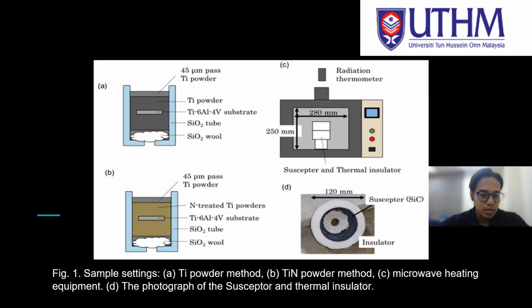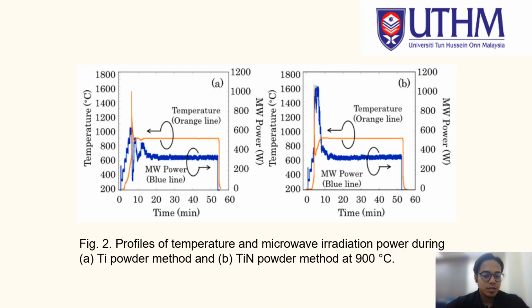The figures show: Figure 1, sample setting, A titanium powder method, B titanium nitride powder method, C microwave heating equipment, and D the photograph of the susceptor and thermal insulator. Figure 2 shows the temperature profile and microwave irradiation power during A the titanium powder method and B the titanium nitride powder method at 900 Celsius. In both methods, the same temperature could be maintained with almost the same microwave irradiation power.